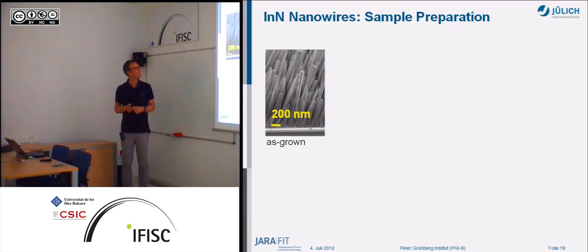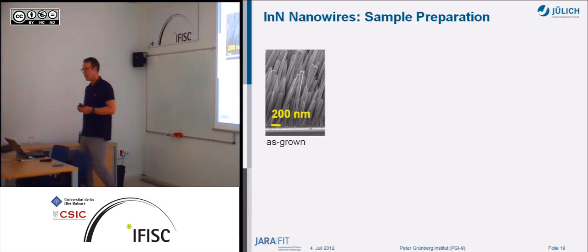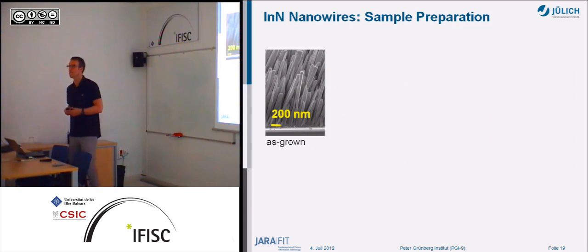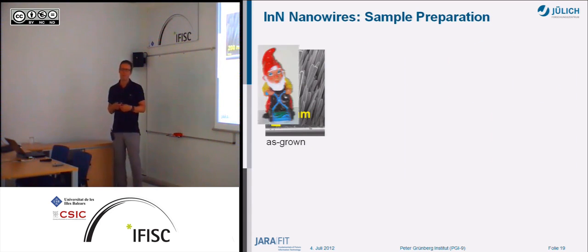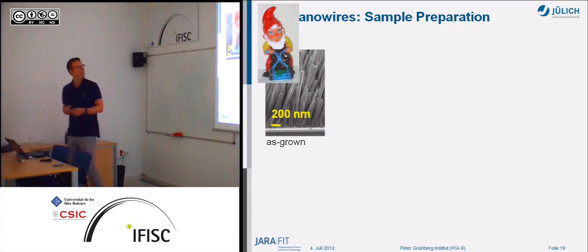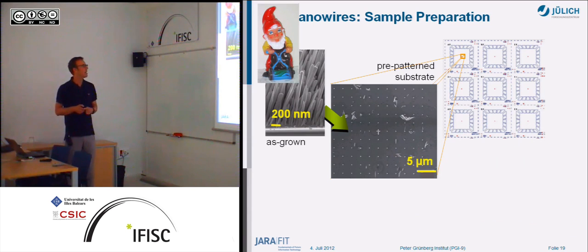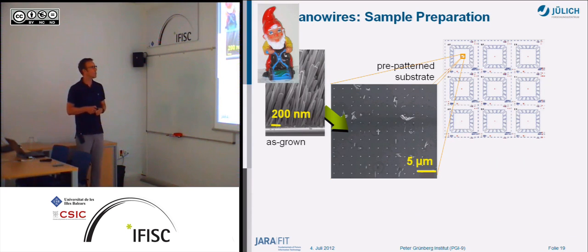So how do we fabricate our nanowires for transport? What we need is we have to put on some contacts to the nanowires. And the first thing we're doing is that we have, not really a lawnmower. It looks like a lawn, these nanowires, but we detach the nanowires from the original substrate, and then we put them on a fresh substrate, which is with alignment markers here. So you have on the new substrate alignment markers.